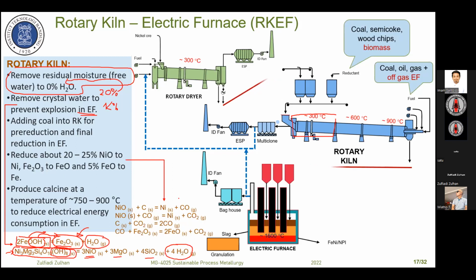And then the last part is around here at the center of the kiln, or in this area here. In the last part of the kiln, we can also reduce the nickel oxide into nickel metal. The common value is around 20 to 25% of nickel oxide reduced to nickel metal, and the rest is still nickel oxide, around 75 to 80%.